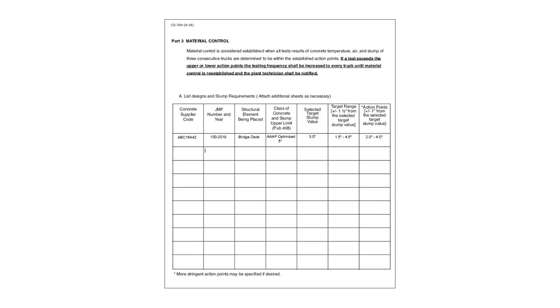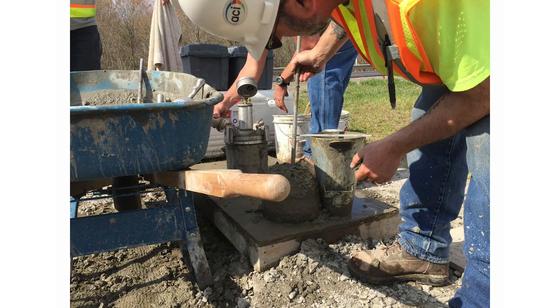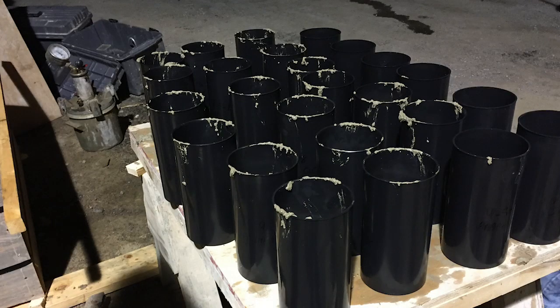If any slump test result falls outside the target range noted on the approved quality control plan, and has not exceeded the upper slump limit of 5 inches for AAAP, immediately perform the air content and temperature tests from the same sample. If the air content and concrete temperature tests are within the specified limits, the contractor may incorporate the material into the work, provided a full set of quality control and acceptance compressive cylinders are molded in addition to the cylinders made for the originally selected PTM number 1 acceptance sample location for compressive strength testing.